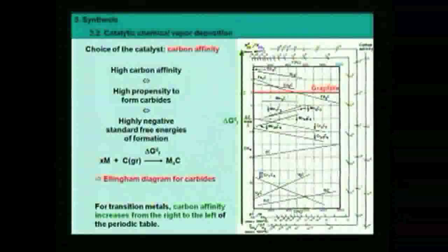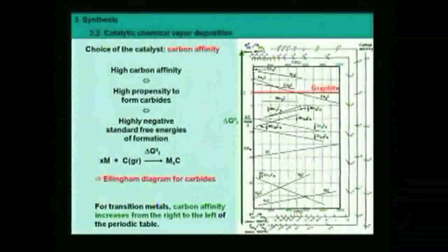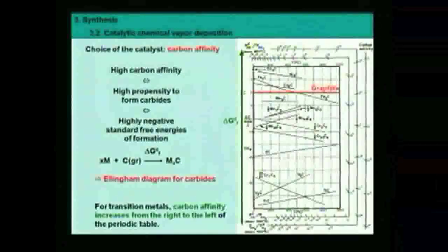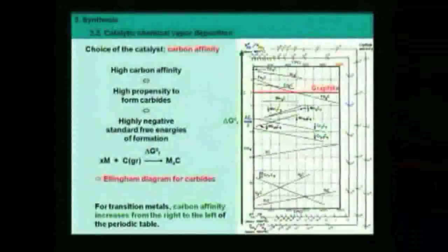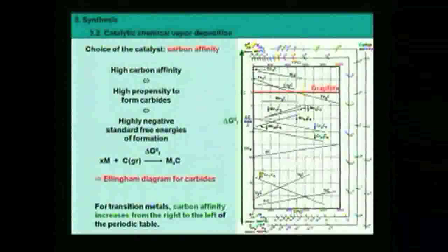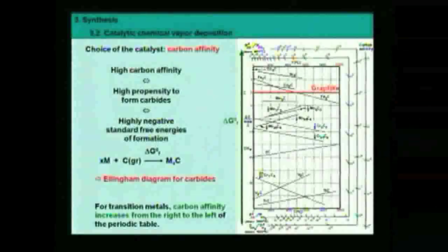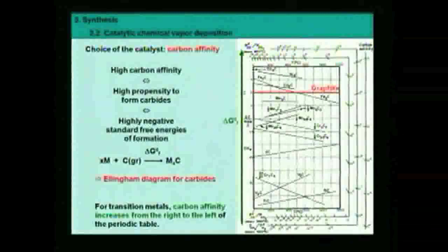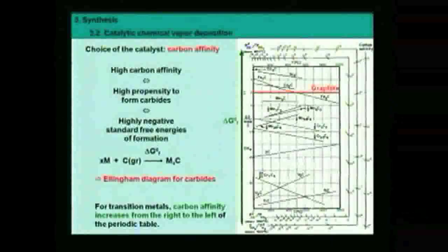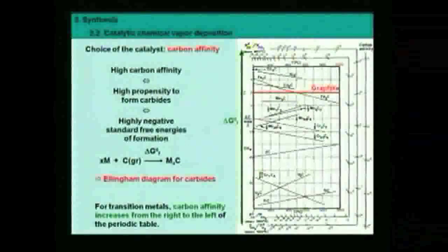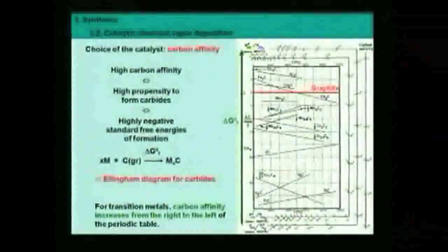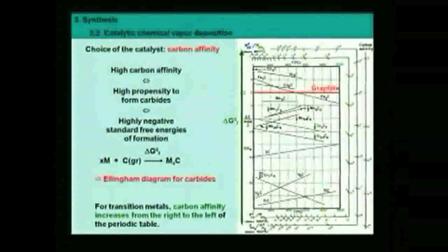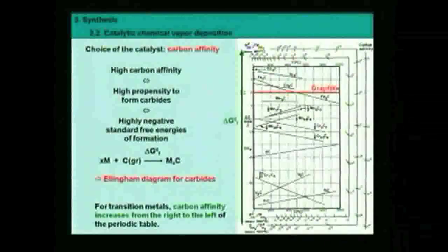On the top here, you've got carbides which are called metastable carbides. Why metastable? Metastable means that they are observed, but they should not be observed from a purely thermodynamic point of view. They are just kinetic products. They should not exist. If you give enough time, they will decompose into more stable compounds. As examples, you've got iron carbide, cobalt carbide, nickel carbide. Again, those are elements that are on the right of the periodic table. And in between, you've got elements that are in the middle of the periodic table.